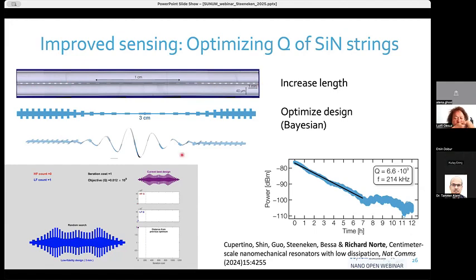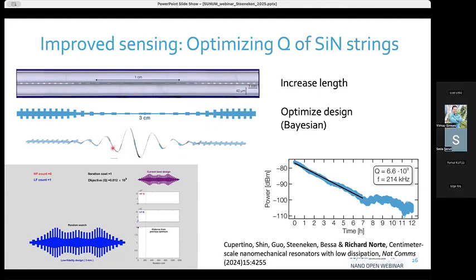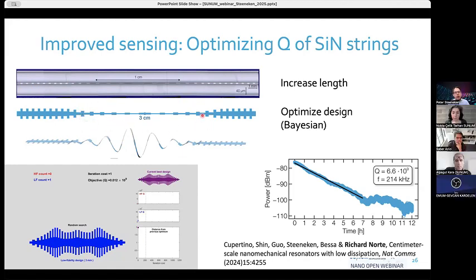And we create a kind of resonance in the middle. And what you see here are special structures which act as mirrors for sound. And by creating these mirrors in the right way, we can confine the acoustic resonances in the central region of the beam, and as a consequence that they're confined, they don't dissipate any energy. And this eventually resulted in resonators that have a very high quality factor. So the quality factor of a resonator is a measure of how many times it basically keeps vibrating after you excite it. So in this case, a record value of more than 6 billion for the Q factor was obtained.